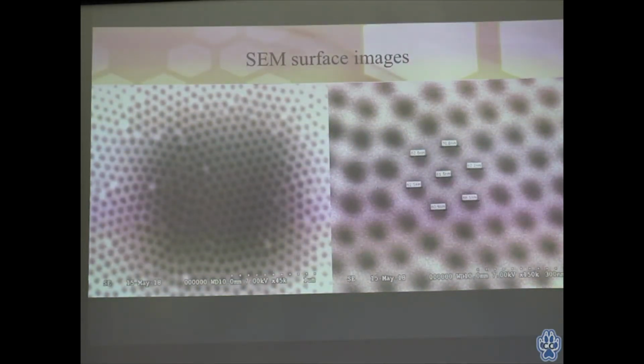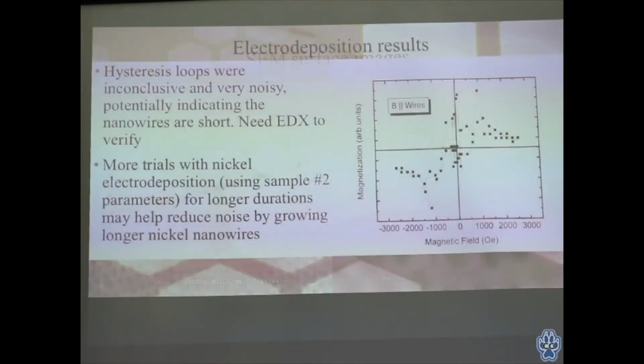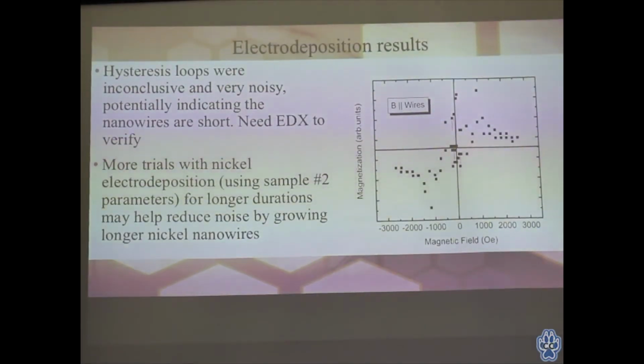So after we had done this, we felt pretty confident that maybe we had some nickel nanowires inside these samples, so we decided to take this specific sample over to the VSM and run a hysteresis curve of it. Unfortunately, the hysteresis loop was inconclusive, as the data was very noisy, as you can tell, potentially indicating that the nanowires are just too short. In future work, we will want to use the same parameters as this last sample, sample number 2, but we believe longer durations of a pulse will help reduce the noise by growing longer nickel nanowires. The curve over here, as you can see, it's not very good, but there is some vague symmetry going from the bottom left to the top right, which we're hoping, if we can grow longer nickel nanowires, that it'll clean up all this mess in between.